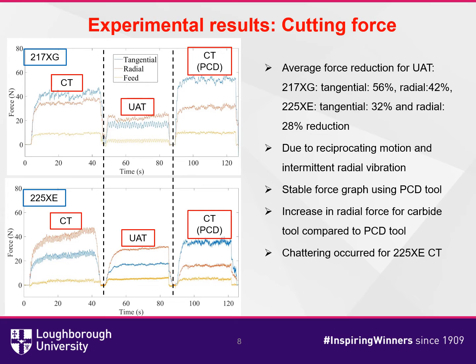A real-time cutting force result is shown in the plot. As it shows in the blue curve, average tangential force for CT was 42.8 newtons for 217xg, whereas for UAT, the average force was 18.7 newtons, showing approximately 56% reduction in the average tangential force. The radial force for the same material was also reduced by approximately 42%. For 225XE, UAT reduced the average tangential and radial forces by 32 and 28% respectively.